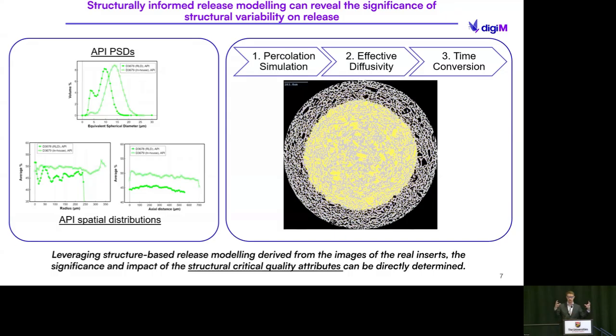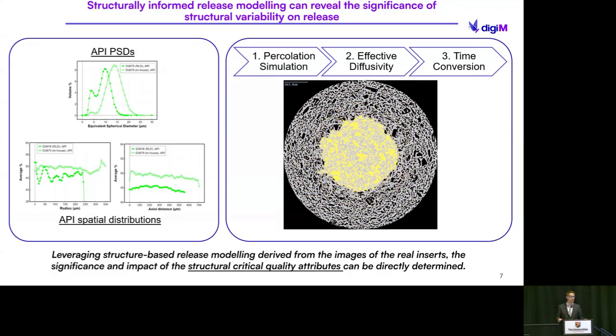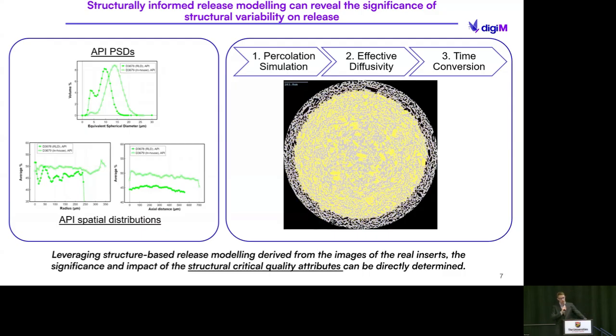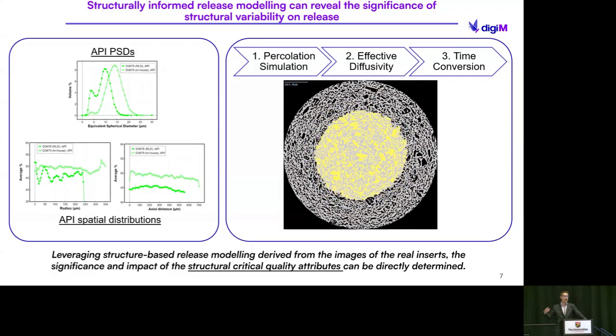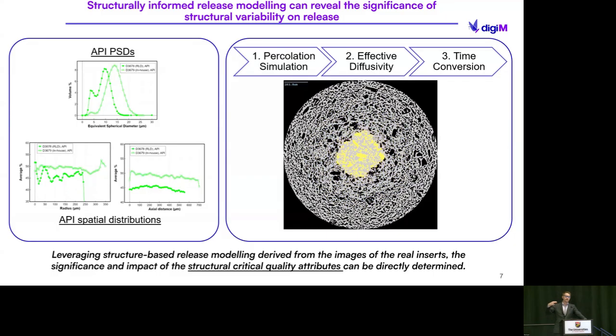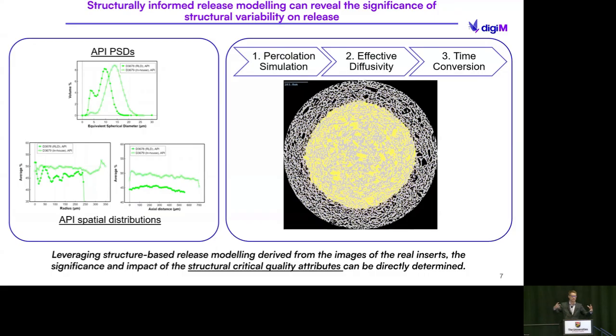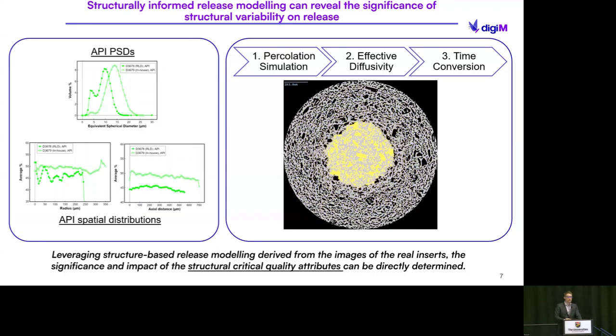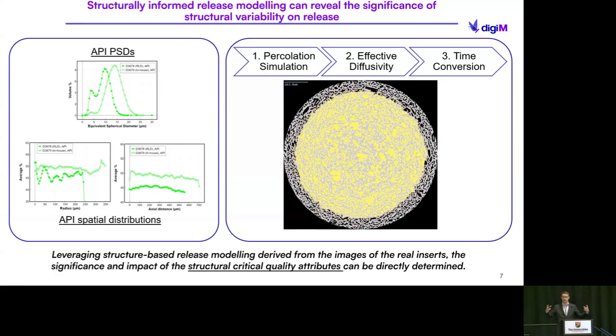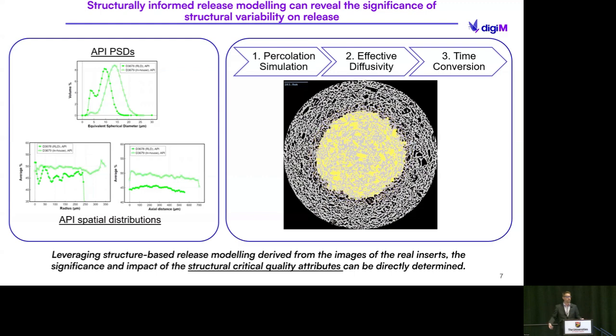So what this repeating video is showing is what monolithic diffusion looks like in this case, where the yellow shows where the API are, and as time progresses, you see it becomes more and more depleted as you go outward. So the release front progresses inward. So we wanted to mimic this in the case of the in vitro release, since the in vitro release, if it's omnidirectional, is going to be going along all of those different directions.